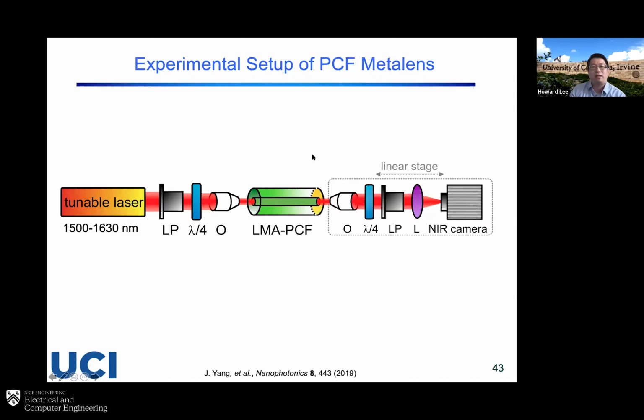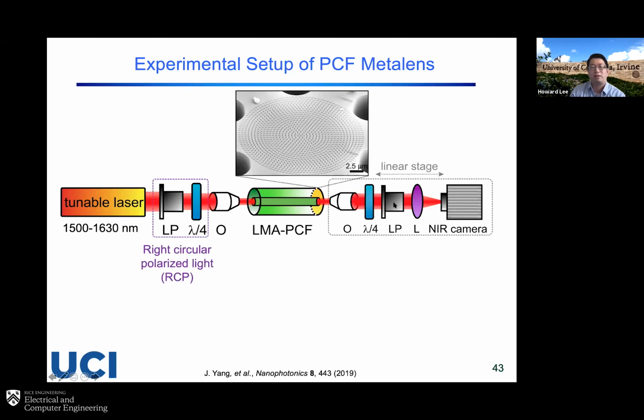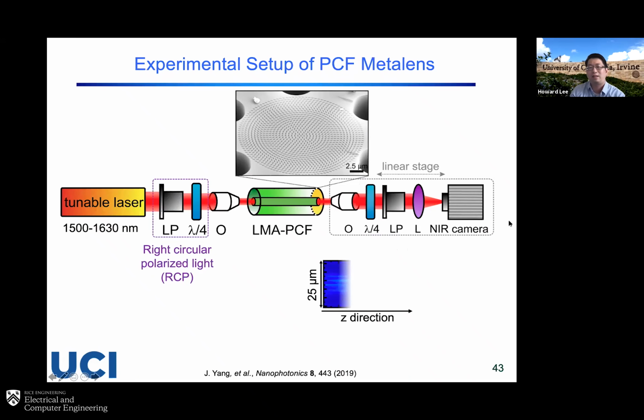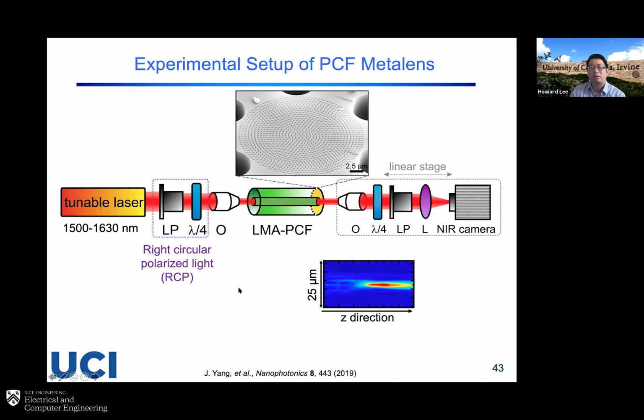So then to characterize this, it's quite simple. We have a tunable laser, we have a metasurface here, we have a camera here, and we launch a right-hand polarization state and collect the left-hand polarization state. And what we also do is to scan the z direction with the camera. So then at a certain position, you find you have a high intensity, which is actually the focus point of the lenses.